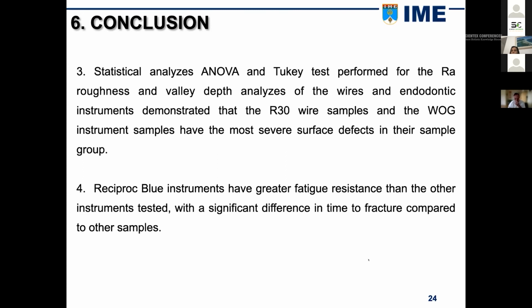Statistical analysis, ANOVA and Tukey tests performed for the Ra roughness and valley depth analysis of the wire and endodontic instruments demonstrated that the R30 wire samples and the WaveOne Gold instrument samples have the most severe surface defects in their sample group. The instrument Reciproc Blue has a greater fatigue resistance than the other instruments tested, with a significant difference in time to fracture compared to the other samples.